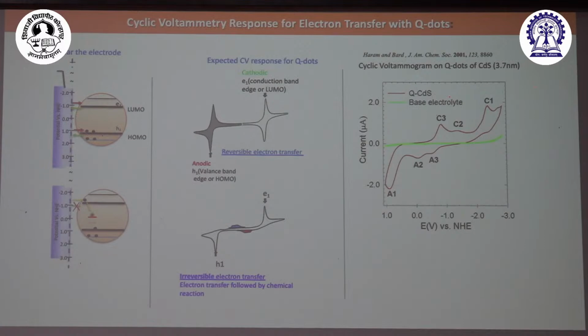This is C1 and this is A1. C1 means cathodic peak, and A1 the anodic peak. From this peak we marked the LUMO, and from this far peak we marked HOMO. And it matched extremely well with the spectroscopic data. In fact, when I got the results, I wanted to publish in JACS. So I went to Alan Bard, my postdoctoral mentor at that time. He was the chief editor of JACS. The JACS office was opposite to my lab.